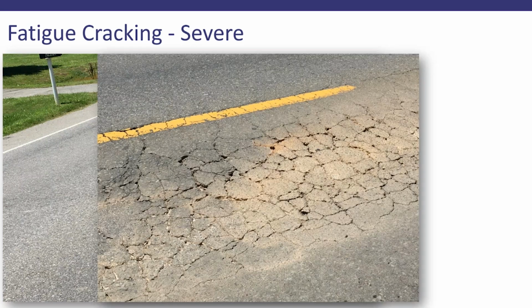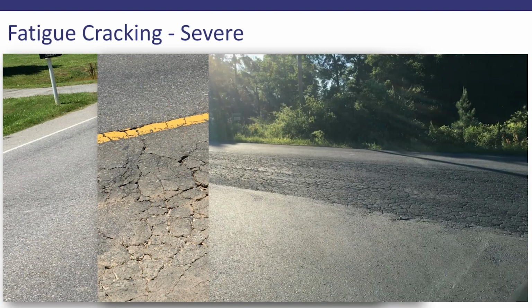There we go. Here's another example. This is some pretty defined alligator cracking, so severe level fatigue cracking. And again, we do see the evidence of that subgrade material being pumped through to the surface. And after that pavement dries, we're left with that residue, so it has a dirty look to it. And then here's one where we do not actually see pumping, but that is some extreme fatigue cracking over in that lane. So lots of interconnected cracks.